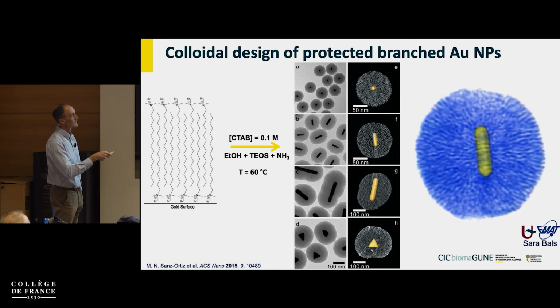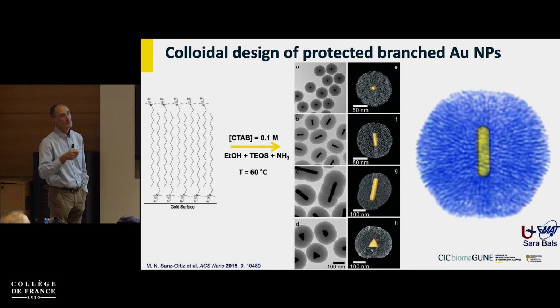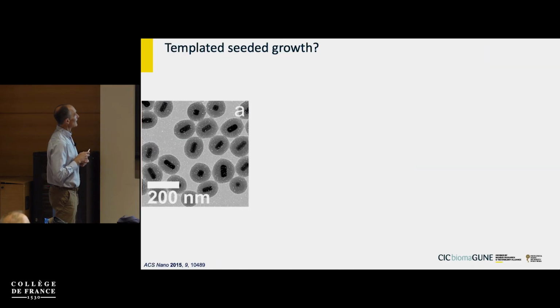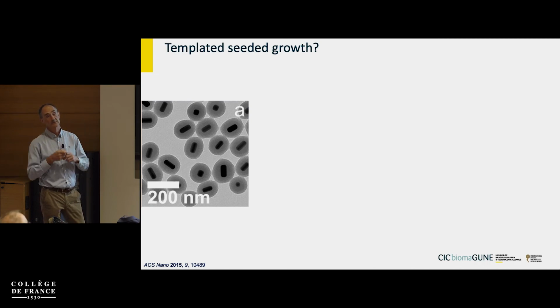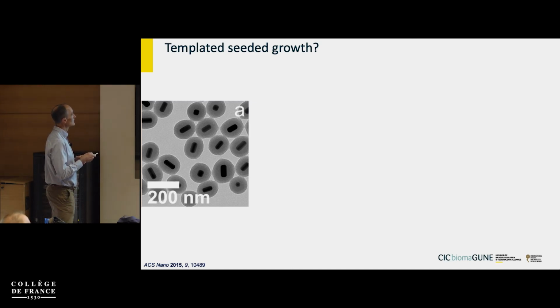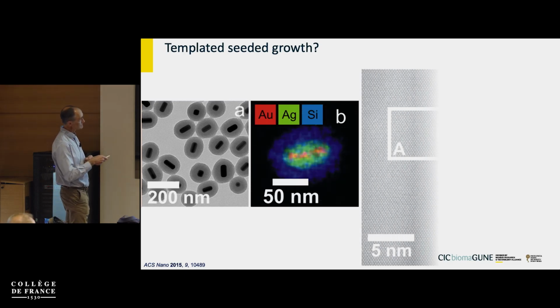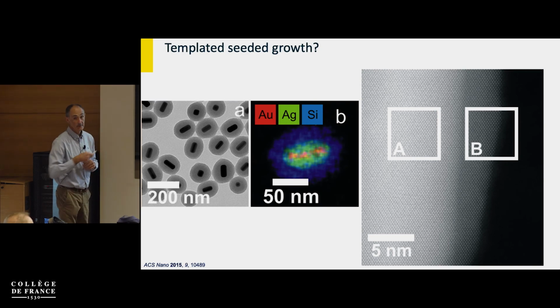And so anyway, they were able to obtain this by playing around with a few parameters in the electron tomography. And then again, we wanted to use the pores as templates to grow tips. Initially we were naive and thought maybe we can grow even silver tips, and then the system will be much more efficient. But unfortunately, after coating with silver, we still only saw nanorods. They do have a silver shell, so they might work, but they don't have the tips.